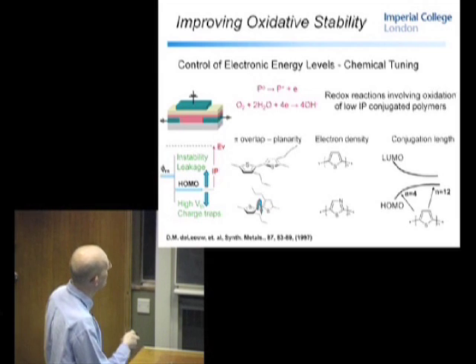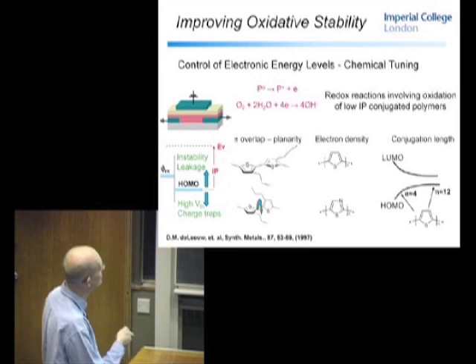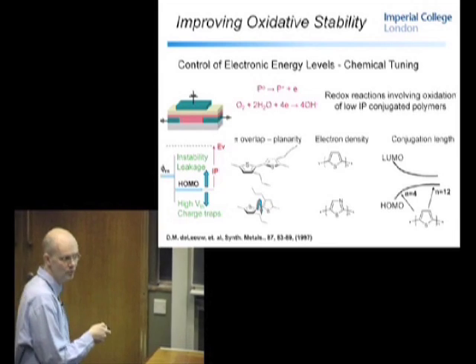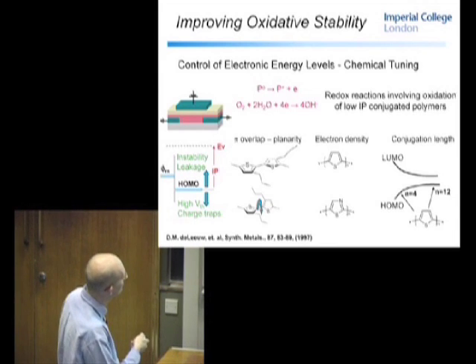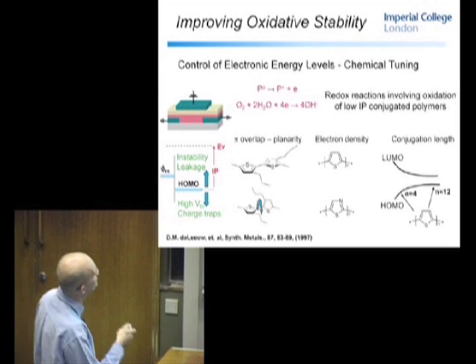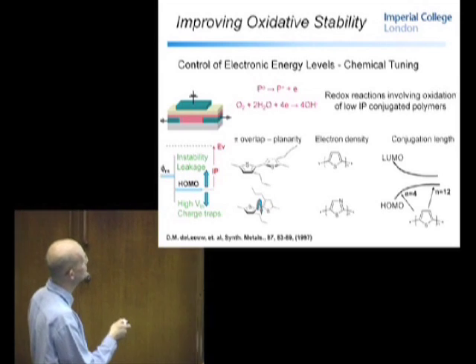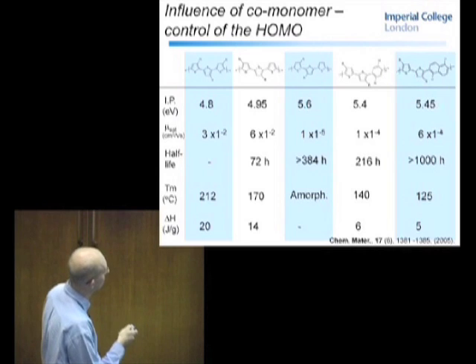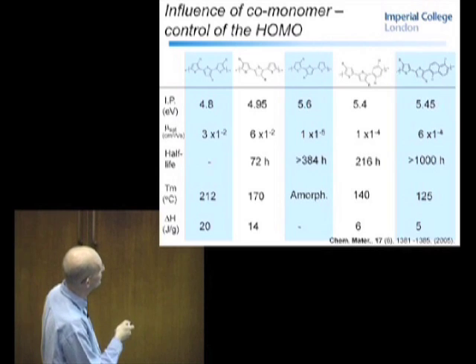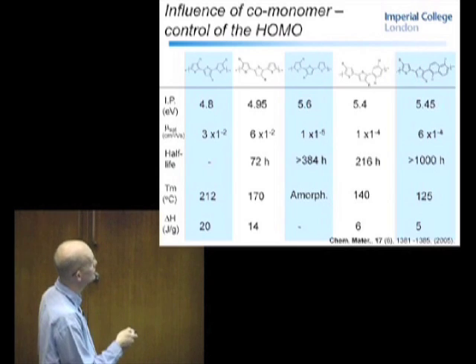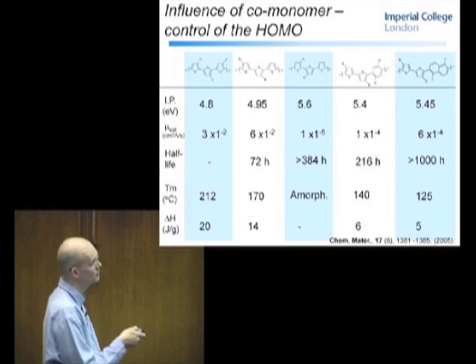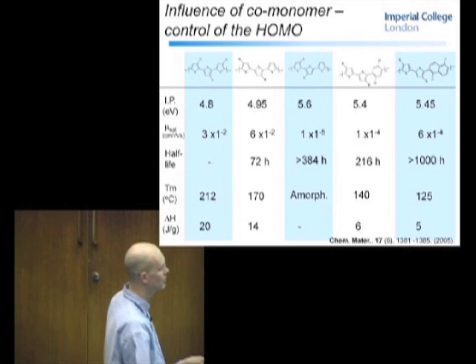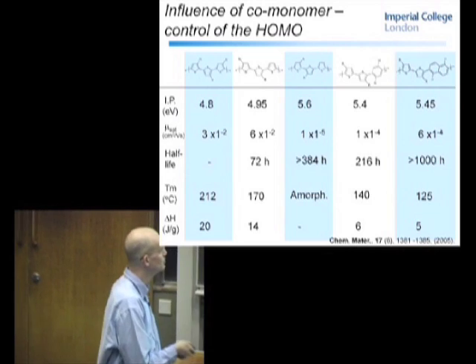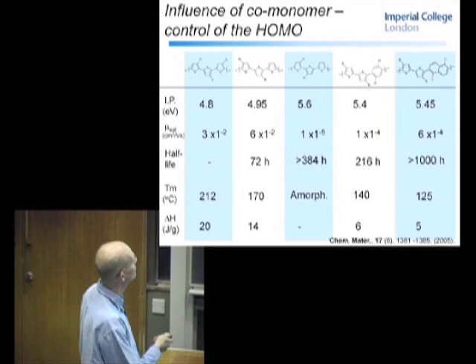But of course, if you push this down too low, you create this barrier to charge injection, and you also lower the mobility. And so this is a problem. It's very much a trade-off. So we started playing around with a variety of thiophene-containing materials, in which case we were able to quite nicely tune the ionisation potential over quite a wide range, but unfortunately mobilities were never that ecstatic. Typically you saw this depressing trend that as you started to increase ionisation potential, you lowered the charge carrier mobility.